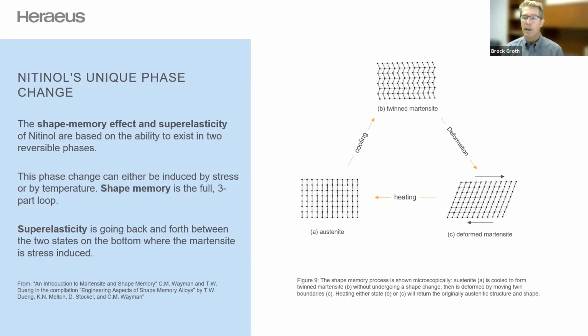And so what happens is you bend the material, and instead of temperature inducing the martensite, you stress induce the martensite. So in superelastic, you are basically moving between the two lower thirds of this triangle. Austenite, you bend it to deform martensite. As soon as you let go of it, the heat in the environment causes it to return to austenite and causes its shape to bounce back. So that's a little bit of superelasticity versus shape memory and the temperature effect of the two relative to the transition temperature. So if we go to the next slide.